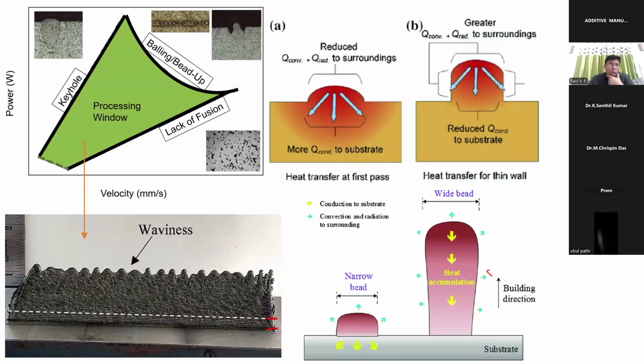This means that though I am using the optimum processing condition, it is optimum only for a few layers, especially when we use direct energy deposition and make thin layers. It is going to be a problem, because when you start the first layer, heat transfer occurs through three different mechanisms: conduction, convection, and radiation. The moment you build the part, say you go 10, 15 layers, heat transfer occurs only through the conduction mode. So obviously there will be enough heat accumulation in the process.